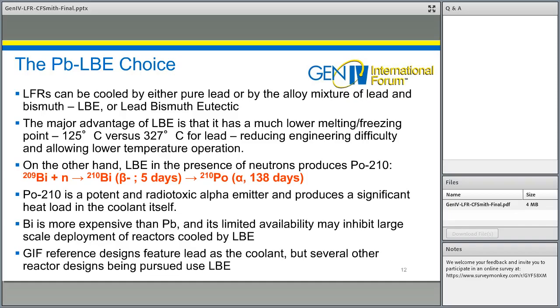On the other hand, LBE in the presence of neutrons produces polonium-210 through the reaction shown in red on this view graph. Bismuth-209, the primary bismuth isotope, reacts with a neutron to produce bismuth-210, which is a beta emitter with a 5-day half-life that ultimately decays into polonium-210. Polonium-210 is an alpha emitter with a 138-day half-life, and it's a potent and radiotoxic alpha emitter, and that toxicity is one of the concerns. And the second concern is that it produces a significant heat load in the coolant itself.